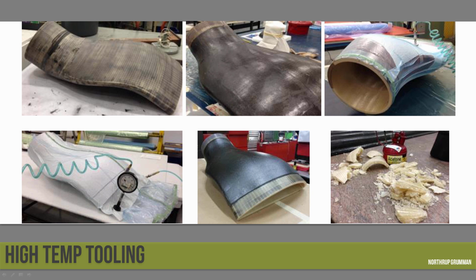So you can see it's an out of autoclave layup over in the top left. They wrap it, they vacuum bag it. There isn't a picture of the autoclave, but it goes through the autoclave process, and then they use acetone to break out large chunks. It's a little bit different process than what I've been doing here in the office, which I'm going to show you.